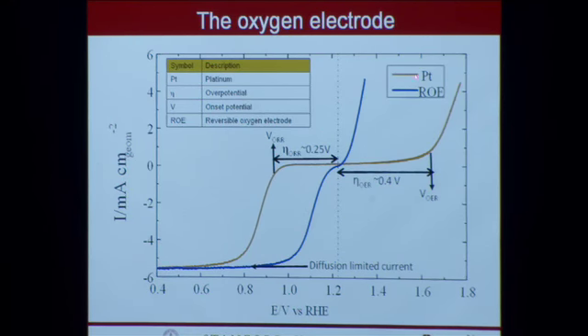If we're going to follow platinum, so this is platinum that we've prepared in our laboratory, you can see here that nothing is going on until you hit an overpotential of 0.25 volts beyond equilibrium. That's just lost energy. And then you start reducing O2, and then you hit some diffusion limited current density based on how much O2 can reach your platinum surface. If we swing to the other side, a positive current means you're doing oxidation. So this means you're oxidizing water to O2.